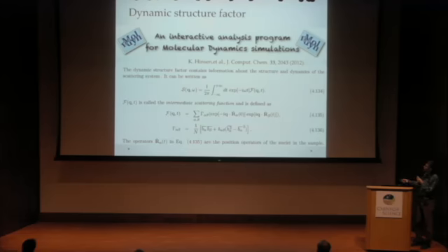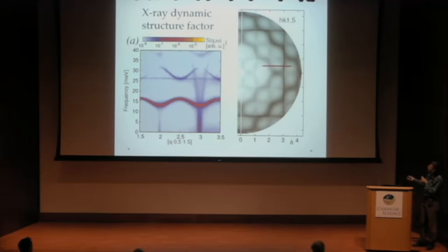We can look at the dynamic structure factor, which is the intensity depending on the momentum transfer and the energy, and it's, as usual, the double Fourier transform of the pairwise correlation functions. And we can look somewhere in reciprocal space, for example, along this line, at what will actually be the contribution of different excitations to the diffuse scattering here. So if you wish, what is plotted here on this line is the frequency dependence of the excitations which contribute to the scattering of our X-ray beam. And already you can see that these diffuse scattering lines, very sharp ones here and there, correspond to a region where there are some excitations with a very steep dispersion in the direction perpendicular to the line.